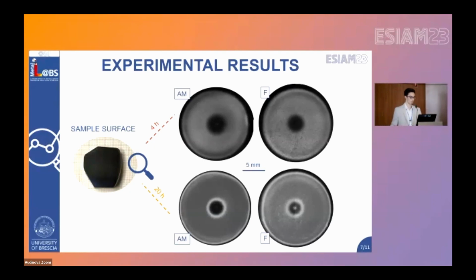And at the bottom, you can look at 20 hours surface erosion, and that is more widely spread. The ring shape is related to the pressure field generated by the sonotrode tip. And these images don't give us much information about the cavitation erosion process.